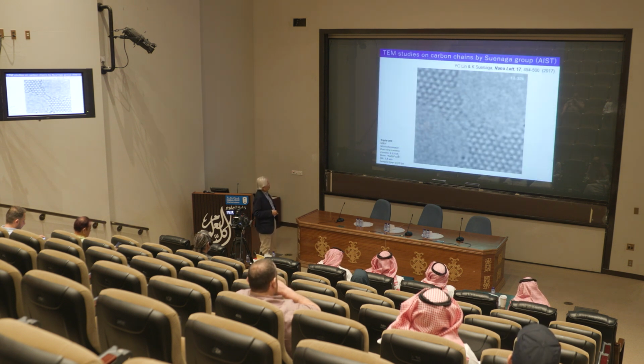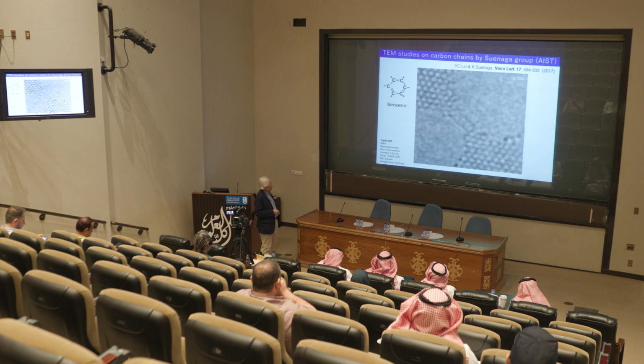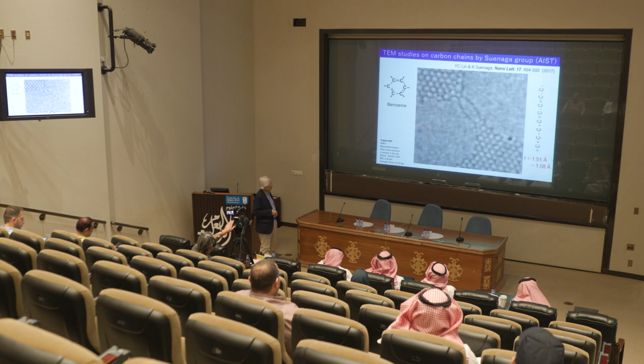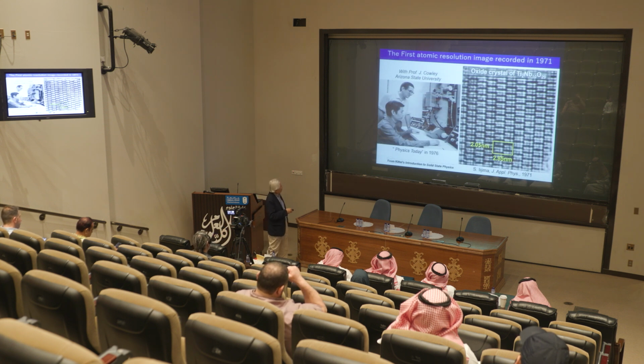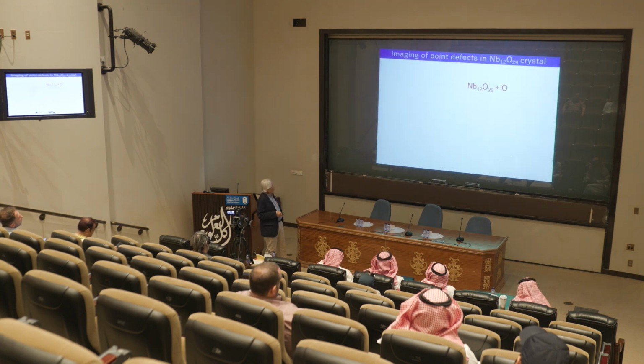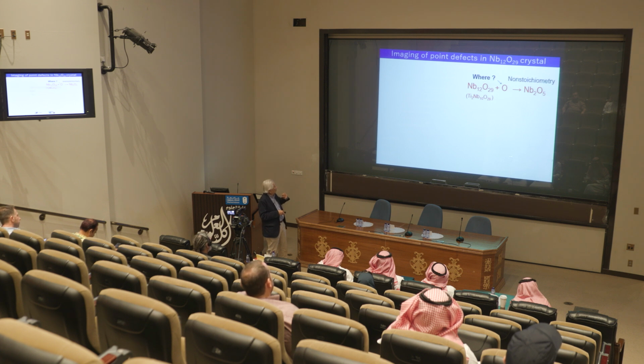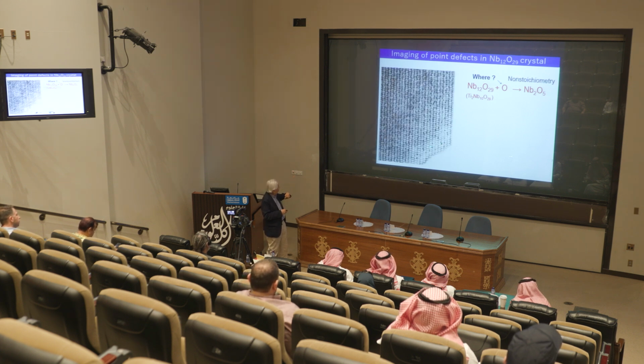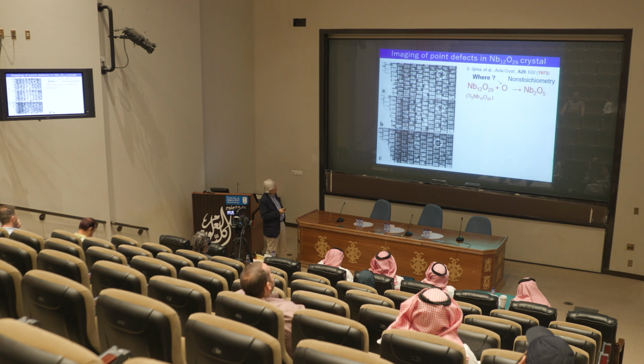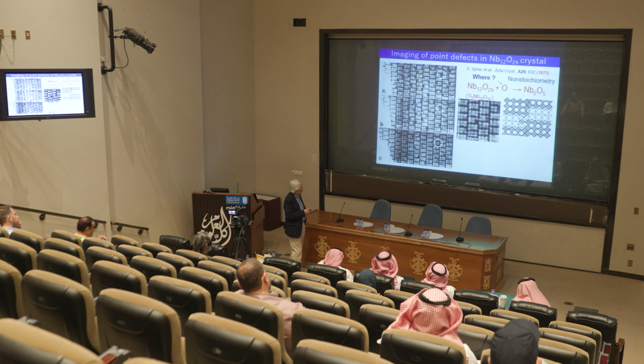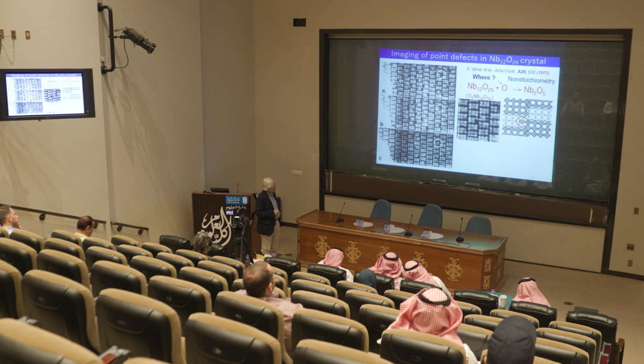Yeah, this is right. I show you this, and then linear change. Come back to here, and this is niobium tungsten oxide, niobium oxide. Because it is a non-stoichiometric structure, oxygen is missing. Anyway, non-stoichiometry, and then already at that time there are a lot of defects there. So this is old work, but I analyzed what happened earlier here. So I can propose this kind of defect in the oxide structures.